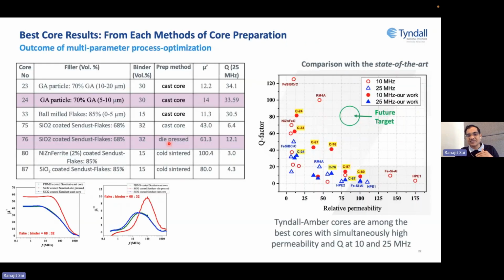Then after some optimization, here you can see the quality factor of the core material. If it is high, permeability is low, and if the permeability is high, core Q is low. The ideal target is to go somewhere around 80 permeability, 80 core Q factor, but we have got somewhere around 40. So we can say that we are halfway down, and there is still enough room to grow in some way.